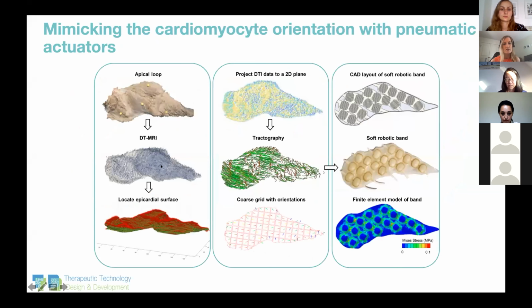And this is diffusion tensor MRI. So basically, you can quantify the direction of fastest diffusion of fluid in the tissue, and that corresponds to the orientation of the cardiac muscle. So we did that, and then we could get this 3D structure of this flat left ventricle, essentially. And then we projected that data onto a 2D plane to allow us a 2D structure where we could perform tractography, which simplifies it and enables you to identify the direction. From that, we came up with a coarse grid with the orientation of the fibers. And then we transferred that into a CAD layout of a soft robotic band.